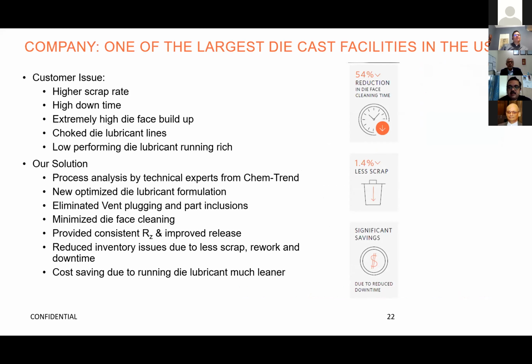Here's another case study from the US, one of the largest die-cast facilities there. The customer had a very high scrap rate, higher downtime, and extremely high die face buildup. Thanks to our technical experts, our sales team in the US did a detailed process study and understood the issue was due to a low performing die lubricant, which the customer had to run richer, that is, at lower dilution, which actually choked the die lubricant lines and spray cassettes. So they came up with a new formulation, and Chem-Trend R&D helped them develop a new optimized die lubricant formulation.